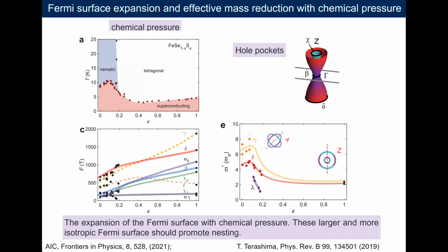It's here. We can follow the behavior of these two pockets from the data. This is the outer electron pocket, which increases, but then we can't see it anymore. And then we can follow the behavior of that very light dominant frequency, which is this lambda pocket, which seems to decrease.